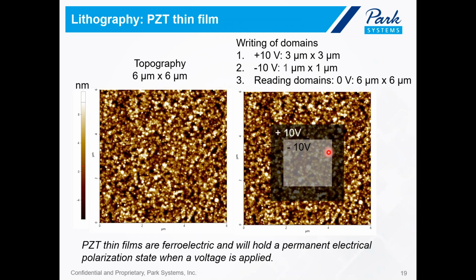So here is a topography image of this lead zirconate titanate, or PZT film. As you can see, there are no specifically noticeable surface features. So we want to perform the experiment and see if we can write on the material, or in other words, alter the electrical polarization direction, and then look at the PFM signal to read it out, read the electrical polarization that we just wrote on the material.